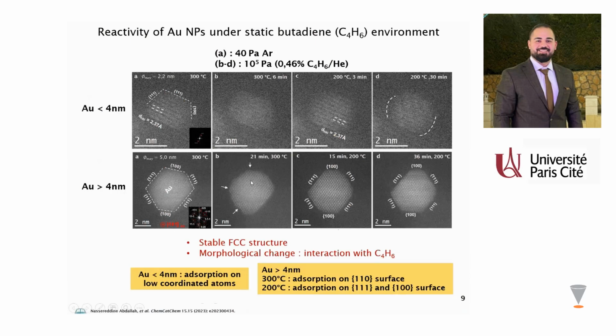As we see, first at 300 degrees Celsius, the particle shows a rounded morphology with different reentrant facets in different regions of the particle, which indicates that butadiene adsorption is located on 110 facets. However, when we decrease the temperature to 200 degrees C, we saw the growth of 111 and 100 facets at the expense of 110 facets, which can indicate that at this temperature the butadiene adsorption is favored on 111 and 100 facets.